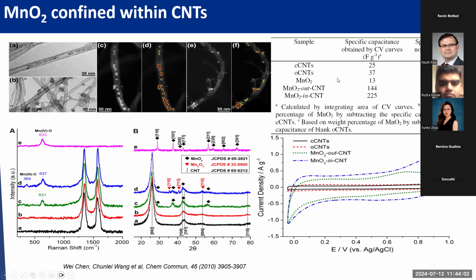The manganese oxide particles we synthesize are basically just from chemical decomposition of the precursor solutions. So those manganese oxide particles have pretty low capacitance, in this case only 13 without any optimization. But when we put the same materials inside the carbon nanotube, the specific capacitance is up to 225 Farad per gram. And compared to another control sample, where the particle is outside the carbon nanotube, the performance is only 144 Farad per gram. So you can see the performance has a dramatic increase compared to just single phase manganese oxide particles. Compared to pure CNT, we have a huge increase of capacitance.